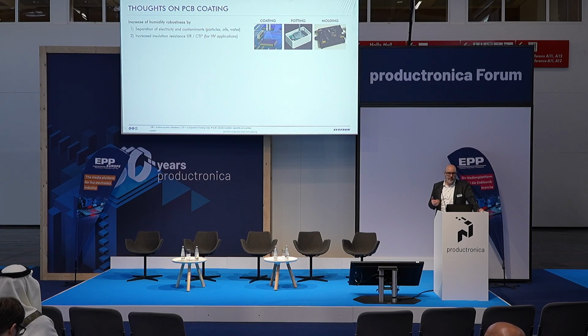So this separation is the main task. And then, of course, especially if you want to go to miniaturization, there's also an additional benefit that you increase the insulation resistance, so you can build components more dense without any issues of electrical breakdown. But conformal coatings, actually every polymer is vapor permeable. So over time, humidity can penetrate into the polymer, into the coating, and also through the polymer. So this is normal, it cannot be changed, so this is for every polymer.